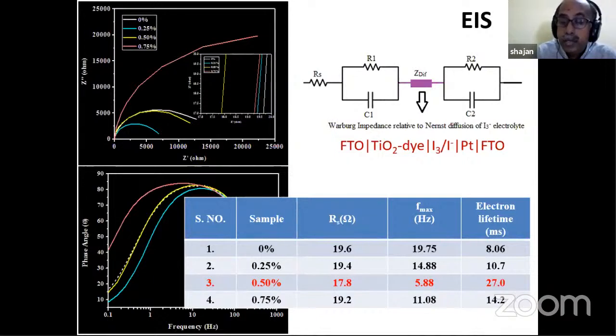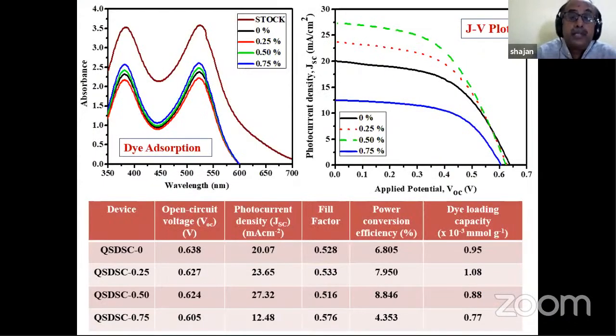And the very important thing we have found out here is the electron lifetime. That is very, very important. You see there is a significant increase in the electron lifetime. Therefore, the diffusion as well as injection is quite possible. That is reflected. Immediately you can see these are the dye absorption studies. You can see for aerogel, this is the reference, and this value is lower. For 0.5, it is improving. Of course, 0.75 is improving, but other factors are not supporting solar cell applications. It may be used for some other applications.